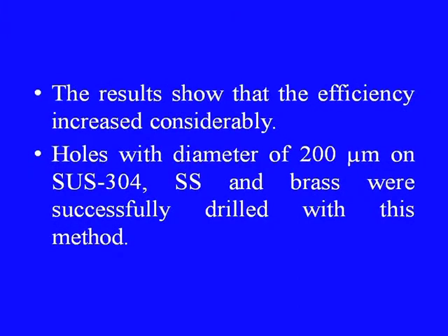The results show that the efficiency increased considerably. Holes with diameters of 200 micrometer on SUS 304 stainless steel and brass were successfully drilled with this method.